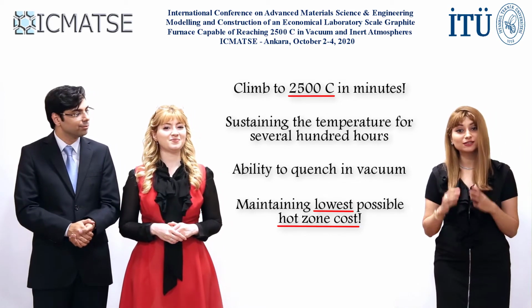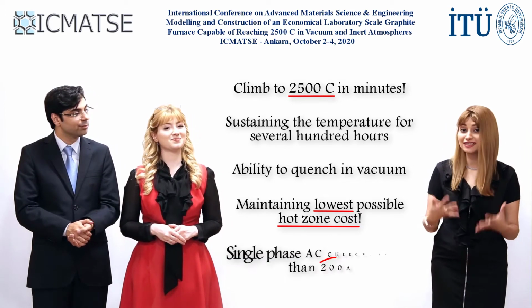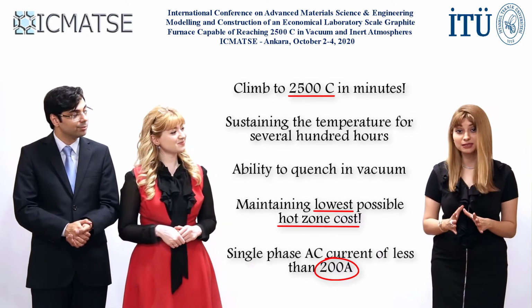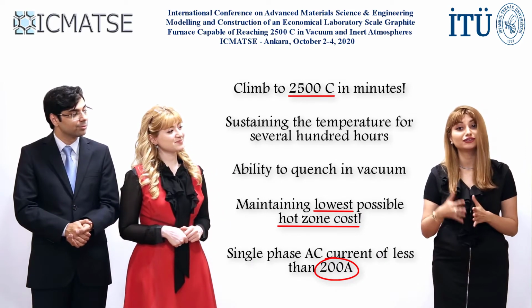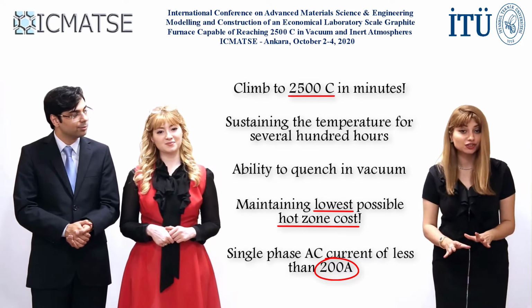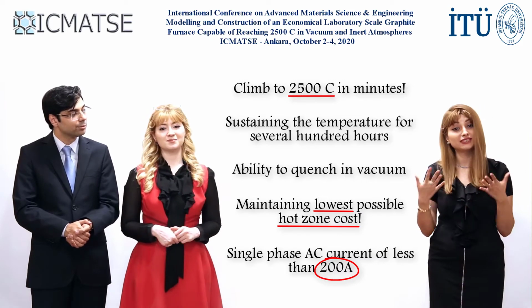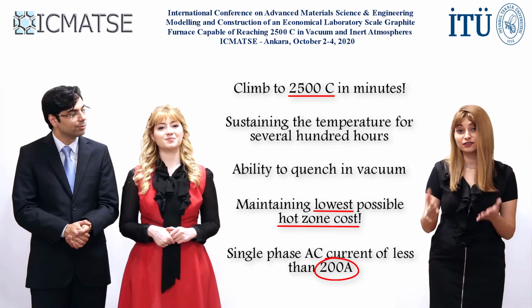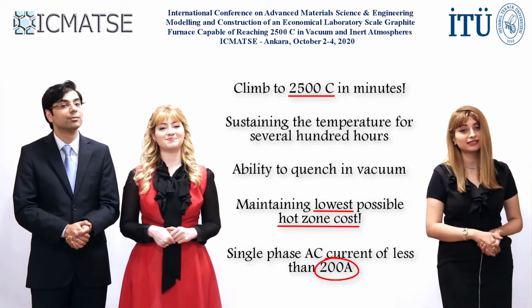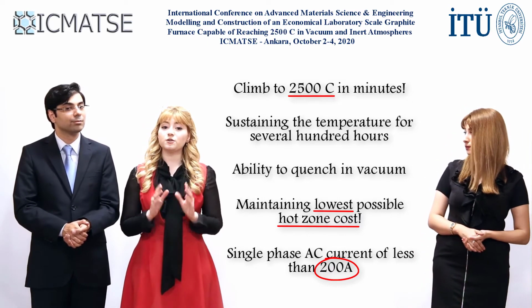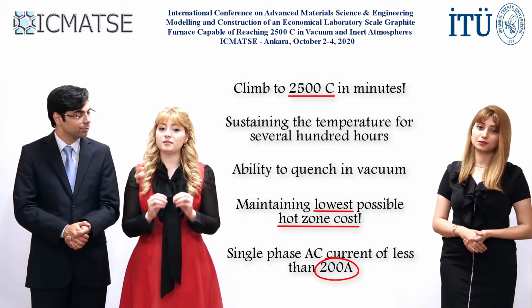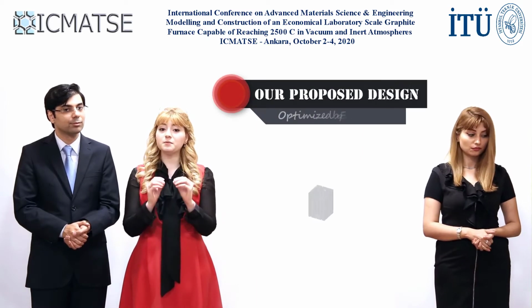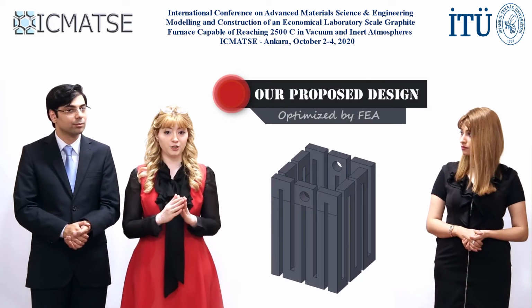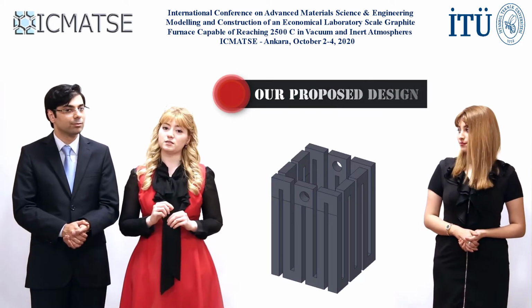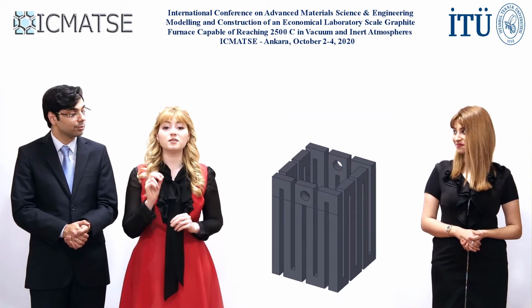We decided that the total current utilized should be less than 200 amperes and it must be operational on single-phase alternating current with the intention of minimizing the cost of the step-down transformer and other electrical components necessary for the system. So we tried a series of different designs which were simulated by finite element analysis, and it was concluded that the optimized geometrical design shown here is particularly interesting for a number of reasons, such as the ability to